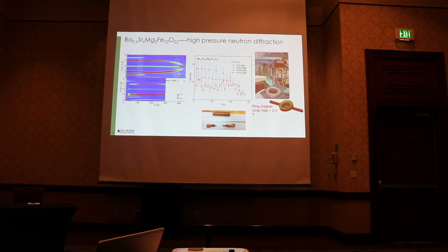What we do is high pressure, since pressure is controlling the system. So we just apply pressure at high doping. What happened is we didn't see much change at small pressure, up to 2 GPa. We didn't see any change for this hysteresis. But that's small pressure. Let's see what happened at high pressure.